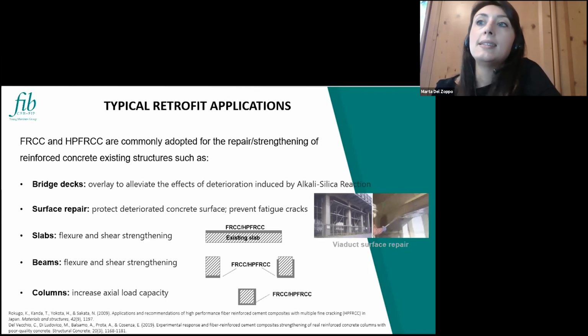In particular, we can do an overlay of the high performance fiber reinforced cement composites over the decks of the bridge, and this is adopted to mitigate the deterioration of the bridges under aggressive salt attacks, and also to improve the durability, of course, of the decks. Such kind of materials are also commonly applied as a surface repair, so without any structural effect, just to protect the deteriorated concrete surface, because of course we have this high durability of the materials.